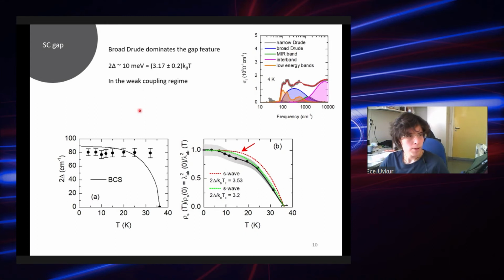Then we move to the superconducting gap, and we wanted to know what the gap value is, of course. We start decomposing our 4 Kelvin spectrum with this Mattis-Bardeen approximation. And what we realize is that the broad Drude dominates the gap feature. So we could reliably get a gap value somewhere around 5 millielectronvolt. In optical spectra, we always see the transition across the Fermi energy. That's why what we see is a 2 delta. But when you convert it with this BCS constant, it shows you that it's in the weak coupling regime. And we couldn't see any clear gap from the narrow Drude component.